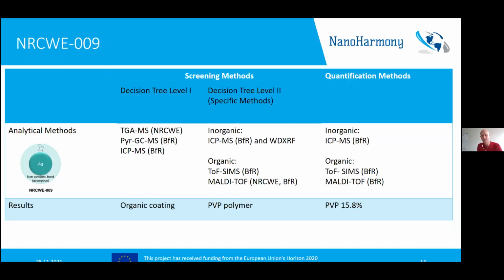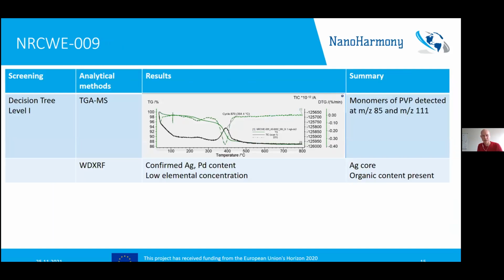For this, the silver compound coated with the PVP polymer, we see a quite interesting result where the TGA-MS finds about 15% organic coating on the material, which is in agreement with the supplier's information. But we also see